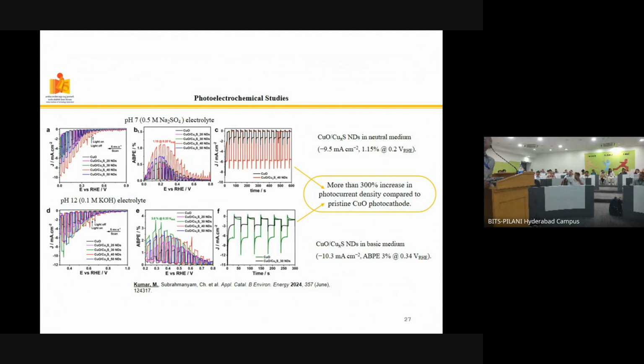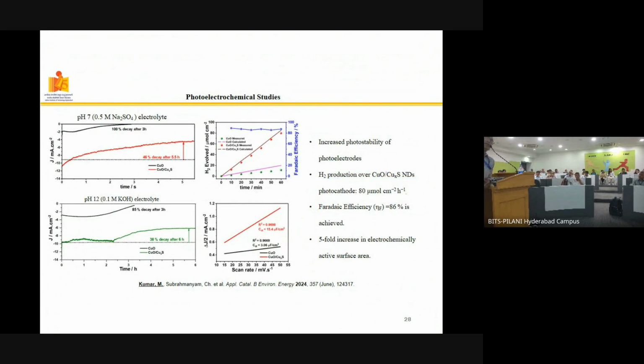So the moment you go from, for example, neutral to basic medium, of course you see that the currents are going to be more, and then the efficiencies are also going to be normally reasonable. Then one question comes to all of us: do we really need the copper oxide copper sulfide combination? If you just look at the catalyst, as I mentioned, the electrode is not stable, which is a known thing. Copper oxide works okay at one particular time, thereafter it degrades. Now over a period of time, of course this is also decaying. Now you see that this degraded, at least in 3 hours, I think 100% decay. Whereas in this case, at least some percentage of activity remained.